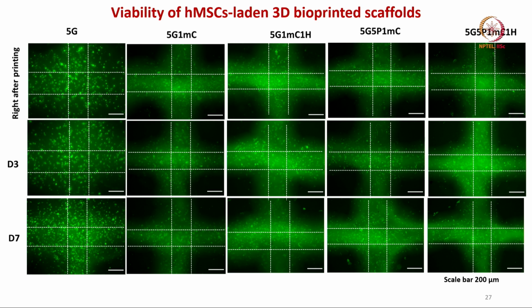Now, for the 3D bioprinted scaffolds, HMSCs were incorporated in the scaffold before 3D extrusion, and then printed. Cell viability was assessed immediately after printing, and after day 3 and day 7 of printing, and you do notice a large number of green fluorescently tagged cells here. The shear thinning behavior of the bioink essentially allowed uncompromised cell viability.